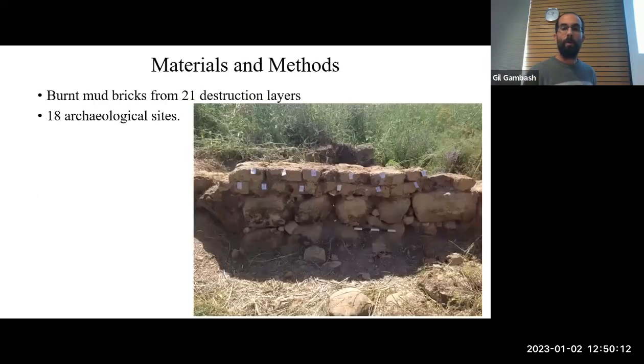What we did, we sampled 21 destruction layers in 18 archaeological sites. This is maybe my favorite mud brick wall, at least the one published in this paper. There's a very nice wall in Megiddo that looks as good. You have the stone foundation here and the mud brick superstructure. This is in Tel Batash, excavated about 40 years ago, and still these mud bricks were fired to such a high temperature that they're perfectly preserved. You can see that they're in their original position.